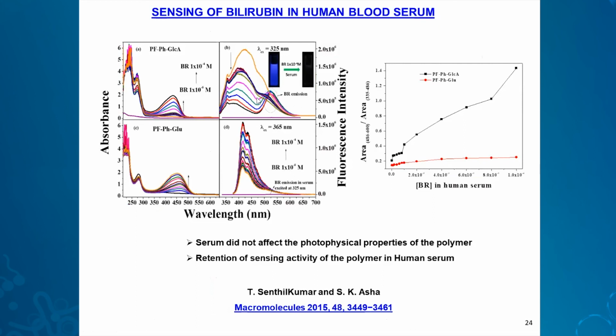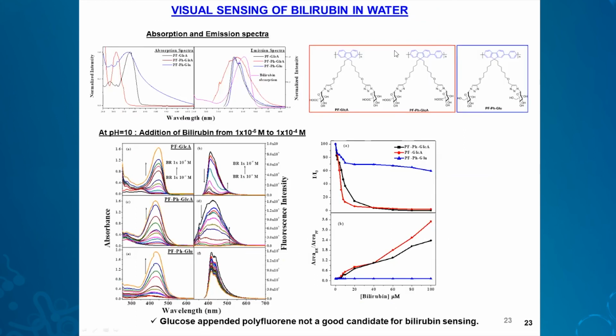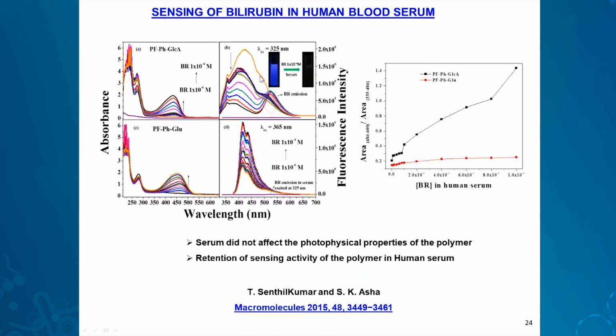Shown here in blood serum, what actually happened was that this homopolymer precipitated out in the blood serum. So eventually, we could take only this copolymer of fluorene and phenyl ring for the bilirubin study in blood serum. Shown here, upper side is this copolymer, and this is in blood serum, the same quenching of polymer fluorescence and increase of the bilirubin emission. This again we tried with the glucose polymer, because it did not precipitate out, but as shown before, it is not a very good sensing agent, and you can see it plotted here also.